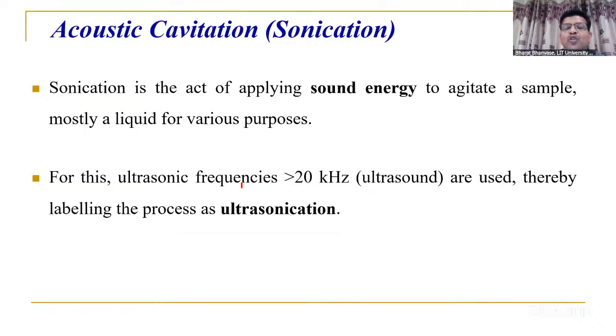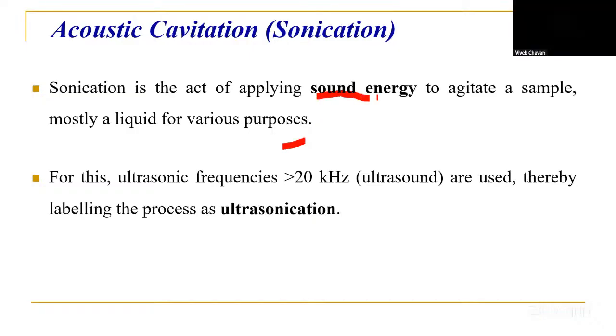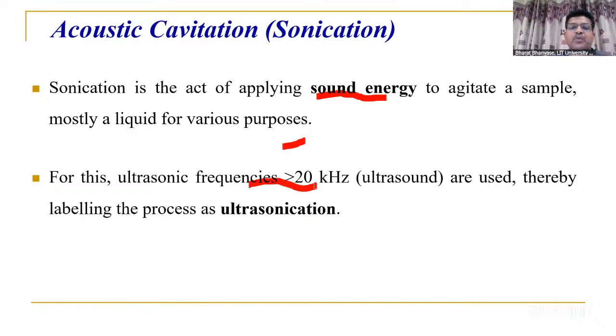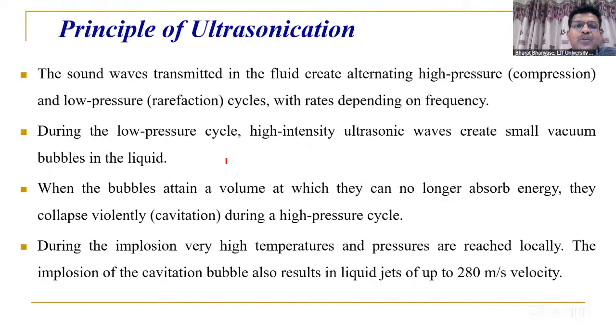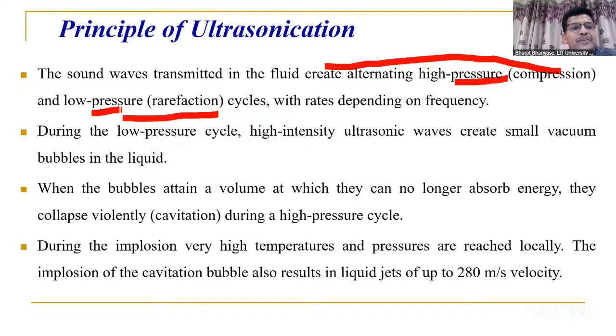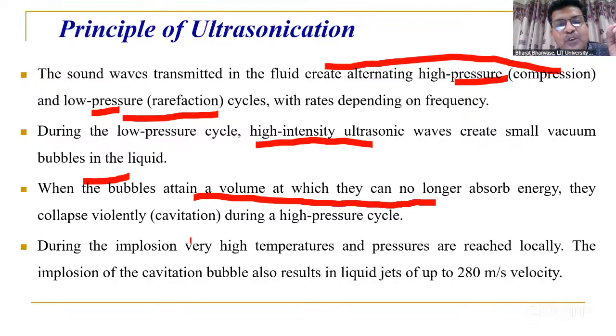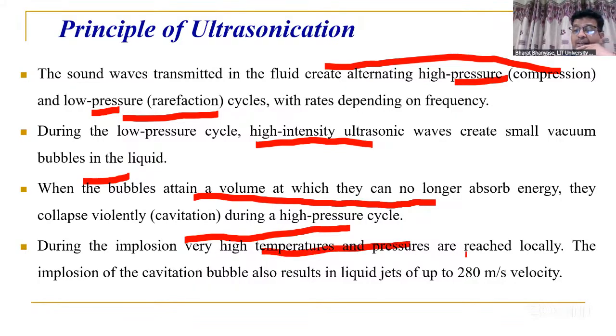Then what is cavitation? That is sonication, you can say, ultrasound. Here we are using sound energy, that is passed through the liquid medium at a frequency greater than 20 kilohertz. What will happen? That will form a wave in the liquid medium, and during this wave there is a formation of compression and rarefaction. That means a high pressure region and a low pressure region. During the low pressure region there is a formation of vacuum bubbles, and the size of these bubbles will increase and they will collapse at one stage. Because of that collapse, it will generate very high temperature and high pressure at a local point.